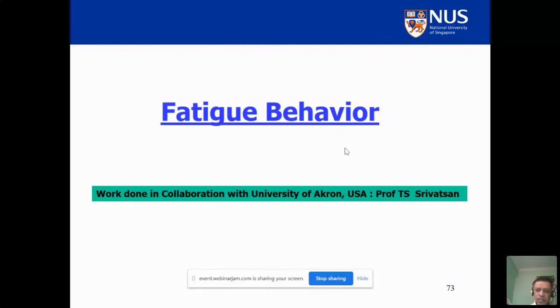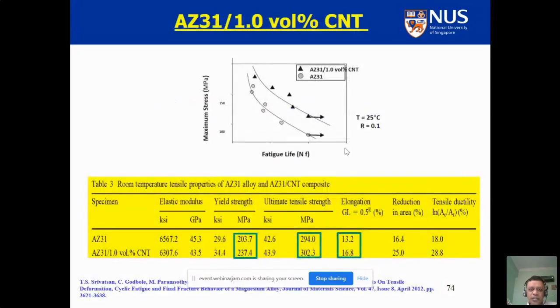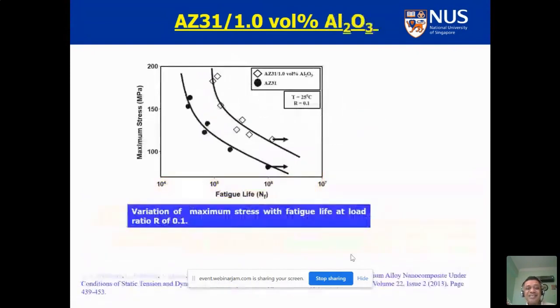Now, fatigue failure is one of the three types of failure which is commonly seen in engineering and biomedical applications. We did some work with Professor T.S. Srivatsan, who is an expert in fatigue. Once again, in this case, we took a commercial magnesium alloy AZ31 with 1 volume percent of carbon nanotube, and you see the stress and number of cycles to failure curve. You can see for every stress level, the number of cycles to failure is more. Besides that, we are also getting an increase in the tensile yield strength and UTS and also the failure strain. So we increase not only the performance in the static loading, but also in the cyclic loading.